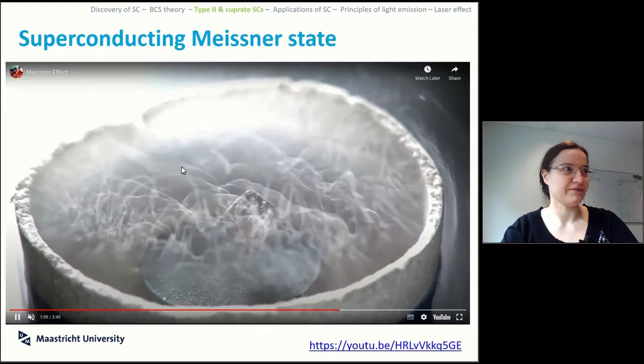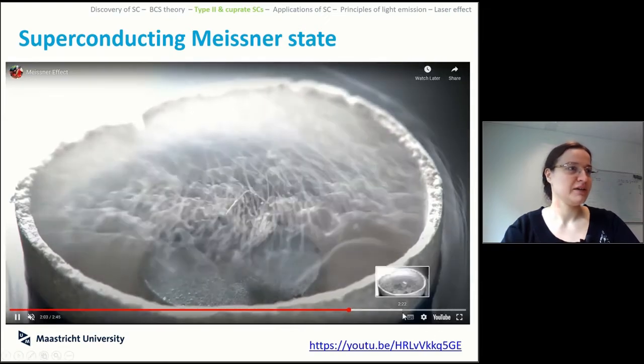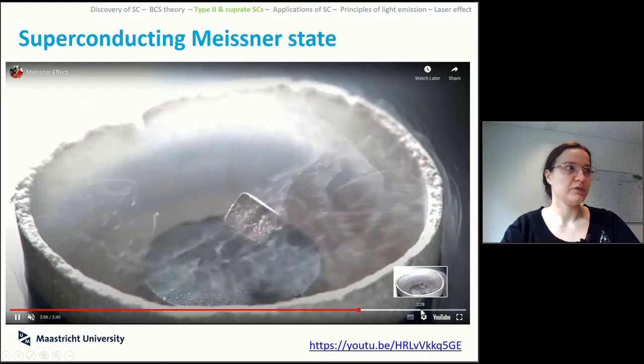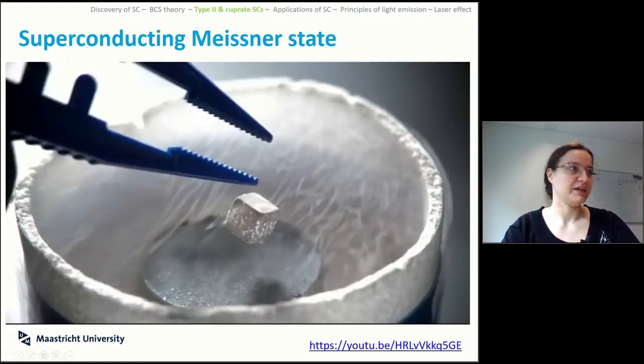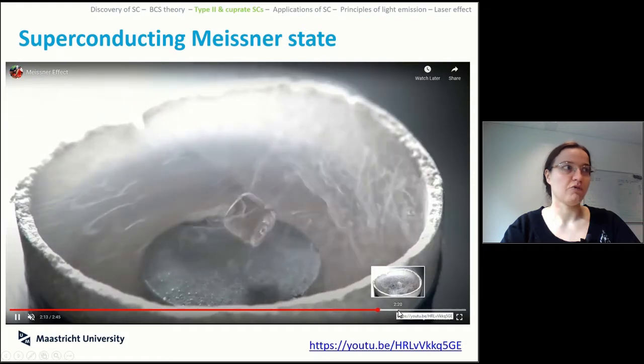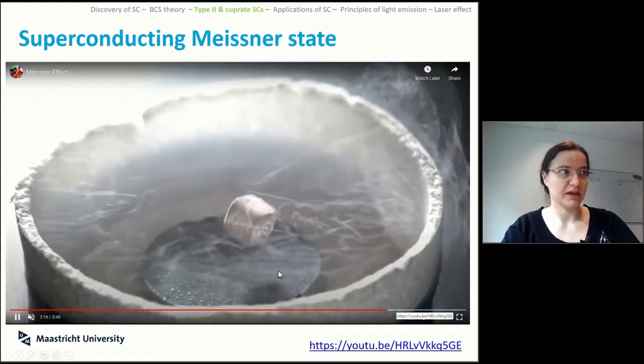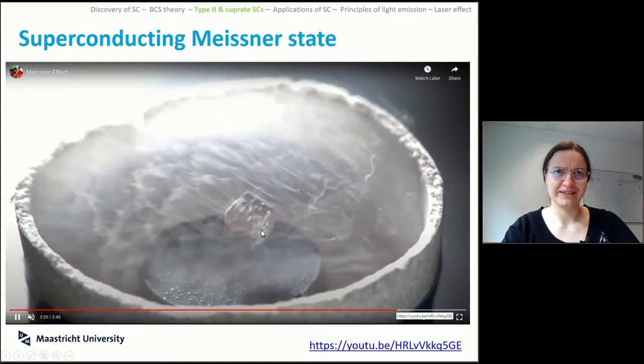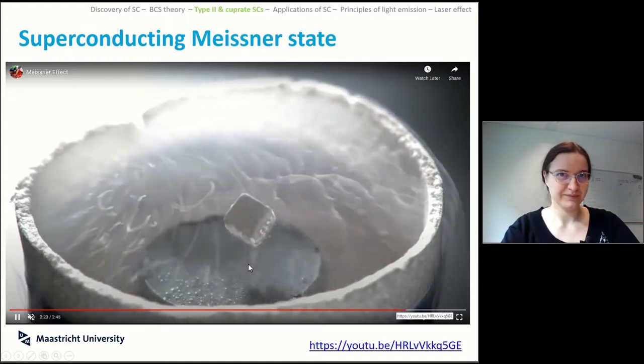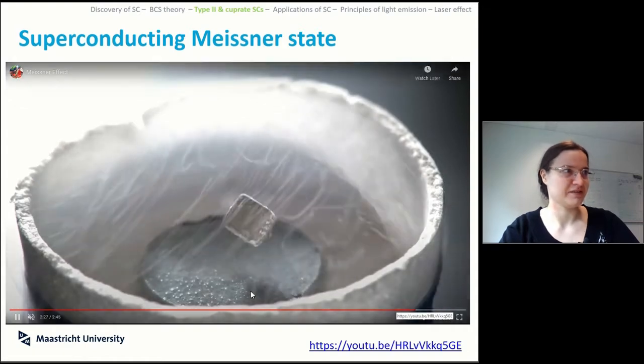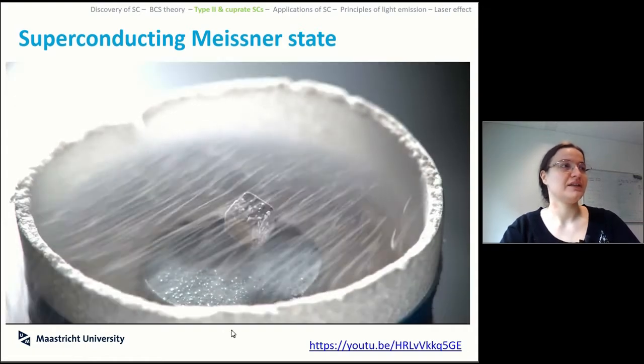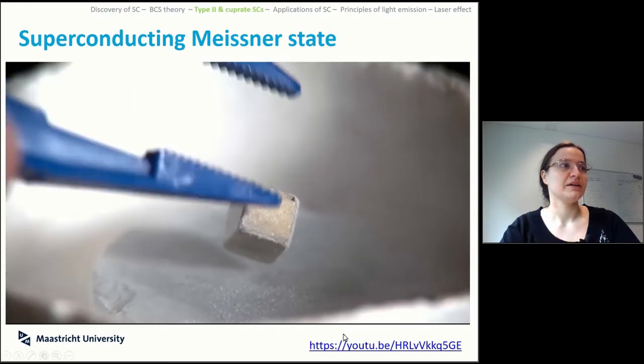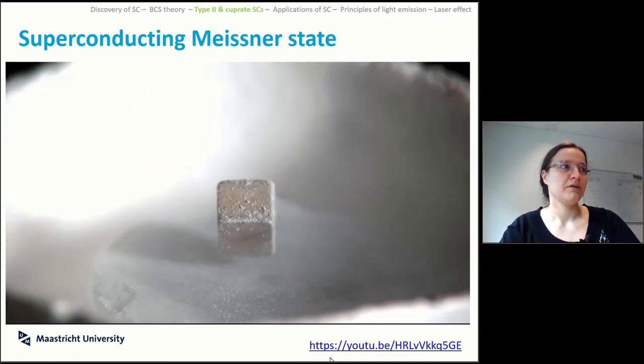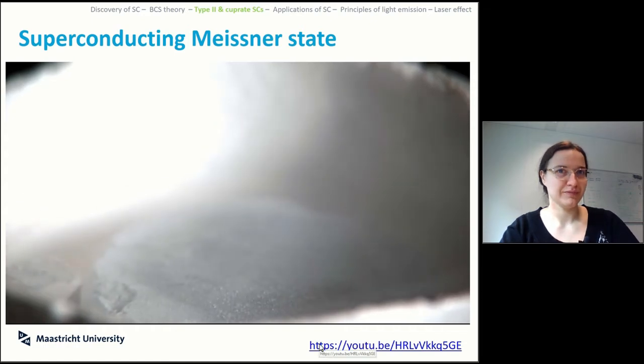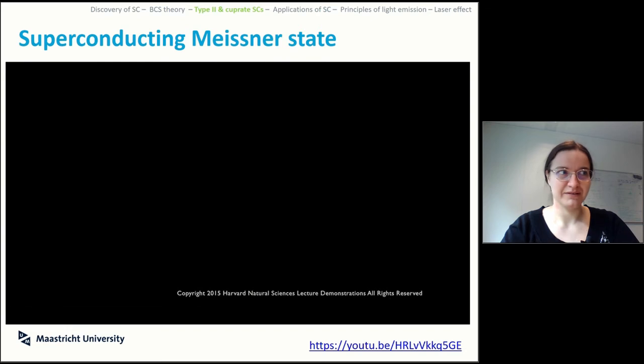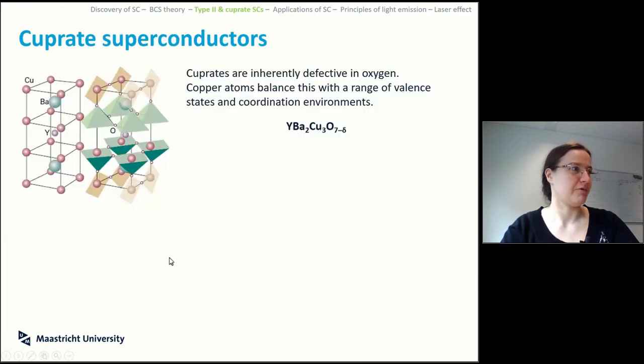So it's a very, very pretty thing to look at. You can notice, of course, since this is cooled in liquid nitrogen, but the liquid nitrogen is slowly evaporating, that this material is warming up very slowly. It's still in superconductive state. You can see how easy it is, how frictionless it is to actually spin something when in superconducting Meissner suspension. But you will notice that as the liquid nitrogen slowly evaporates, the material is actually starting to warm up. When it warms up, you lose the Meissner state. When you lose it, your magnet drops.